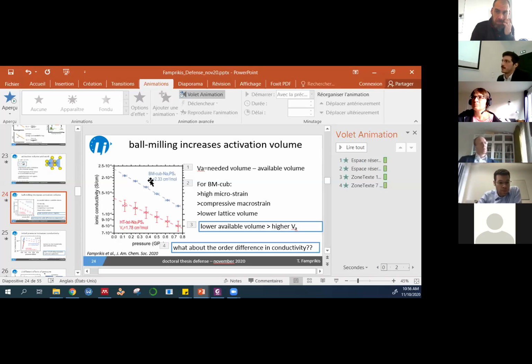And I guess we need to remember that what we're actually looking for is not necessarily the total sodium or lithium content, it is the mobile sodium or lithium content, which further complicates this idea. So it's a combination of that. You would like to know the number of defects, but in particular also the number of mobile species compared to the less mobile ones.